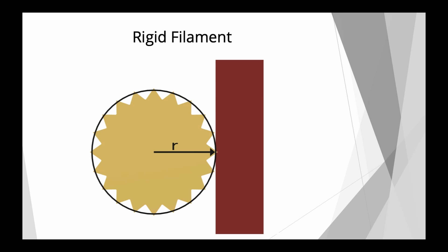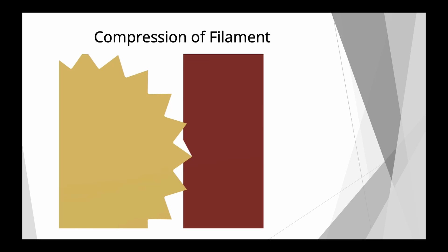The other factor that influences your e-steps, if you would calibrate it this way, is the compression of the filament. So you might have noticed that if you calibrate your e-steps without a hotend, so just not extruding it but the filament just being pushed out of the extruder, and then you calculate your e-step, you get a lower value than if you would use a hotend.